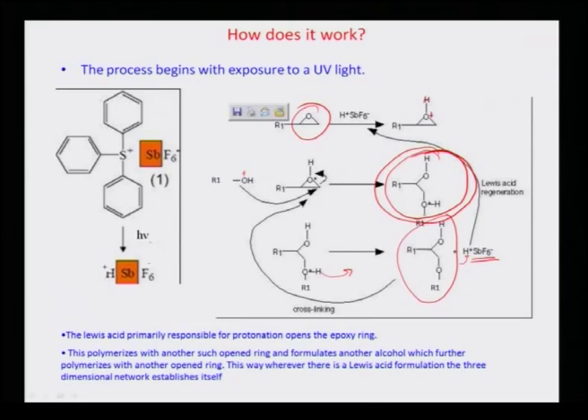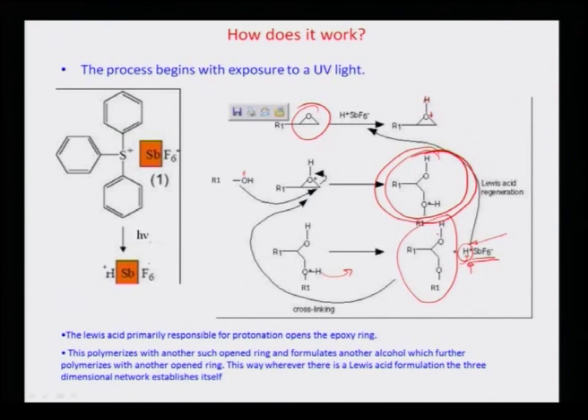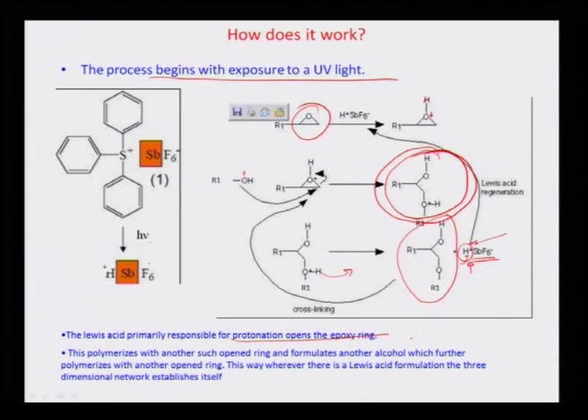You have a cross-linked network of polymers wherever there is an H+ ion or proton generated — meaning wherever there is exposure to light generating H+ from the photo acid generator, there is cross-linking which makes the polymer matrix solid. That is how UV exposure causes cross-linking of SU-8 negative tone photoresist. Protonation, opening of the epoxy ring, and cross-linking are the three steps which polymerize the resist in the areas exposed to light.